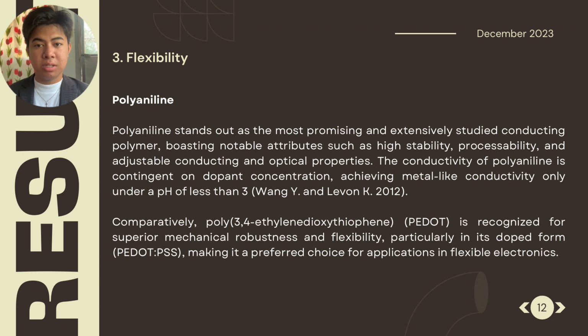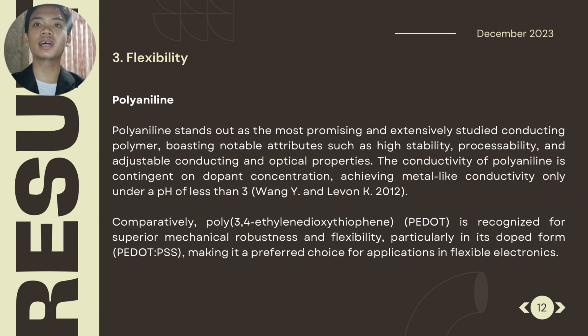This method involves immersing PANI in a solution of dopant such as sulfuric acid or hydrochloric acid. The dopant molecules insert themselves into the PANI chains, which increases the conductivity of the polymer. Their work emphasizes the importance of doping strategies in enhancing the electrochemical performance of polyaniline. By summarizing recent developments, this review provides valuable insights into the ways in which doping techniques can be employed to optimize the functionality of conductive polymers for energy storage applications.